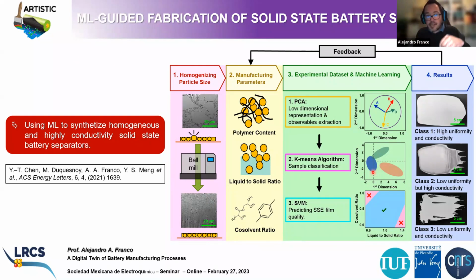And then we feed these classes into a supervised machine learning technique, support vector machine, in order to construct these kinds of phase diagrams, which can guide you in the choice of the parameters that you need to adopt in order to fabricate the separators with high uniformity and high conductivity.